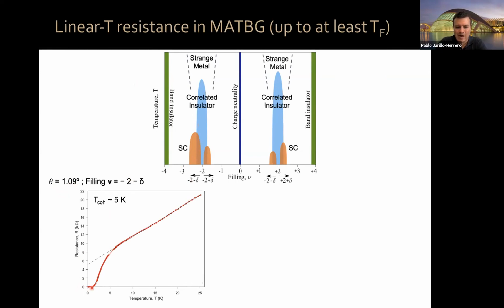You can see that once you get out of the superconducting state, the resistivity is very linear with temperature. And 25 Kelvin is a very high temperature for the system, because it is actually above the Fermi temperature of the system. Remember, because we have a moiré superlattice, the densities that we're talking about in these systems are extremely low. So the Fermi temperature is very small.